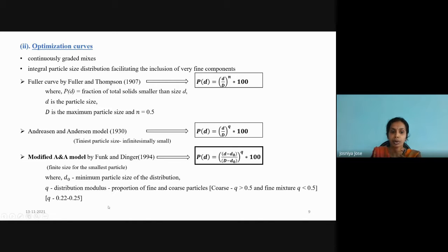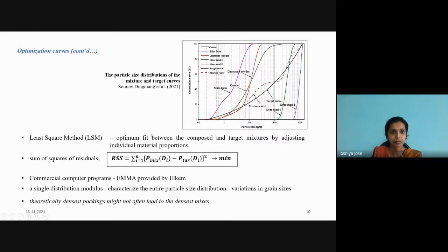And this was introduced in the modified Andreasen and Andersen model, where D0, that is the minimum particle size, was also considered in the distribution. So for UHPC mixes, the Q value can be assumed to be between 0.22 and 0.25. And researchers have mostly used this modified Andreasen and Andersen model for optimization of UHPC mixes. This model specifically acts as a target curve, and different combinations of materials are adjusted so as to form the mixture curve, that is the composed mix. And the deviation between this composed mix and the target curve is calculated using the least square method. And when this deviation is minimum, we can treat that mix as the best one.